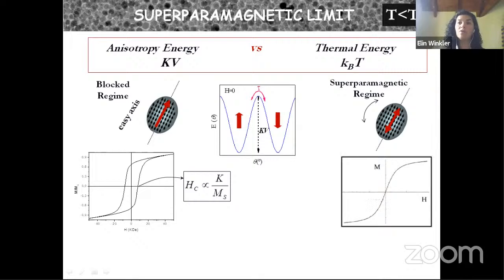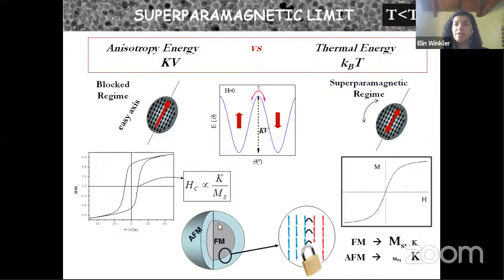So if we want to design a permanent magnet, or a material for high density data storage, where we want the magnetization to keep along one direction, because in that way we codify the information in a magnetic way, where each bit is related to one orientation of the magnetization, we need to increase the anisotropy energy. One way to do that is to increase the volume, but we cannot do that because we want to reduce the size of the material. So the other way to do that is to increase the magnetic anisotropy. And how can we do that? Well, by fabricating core-shell nanoparticles.